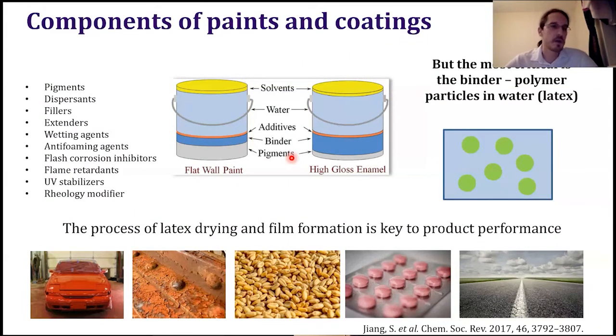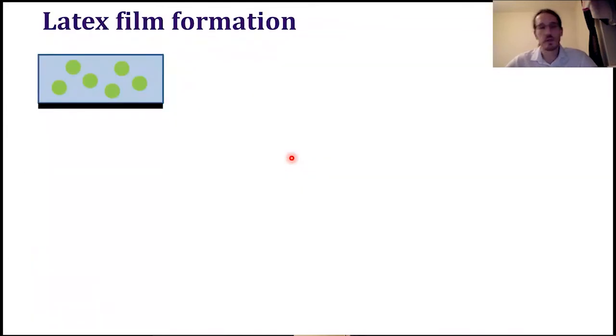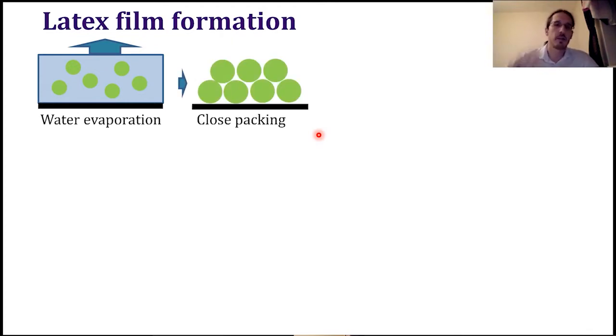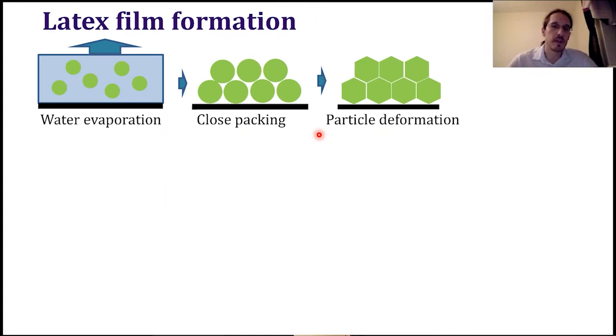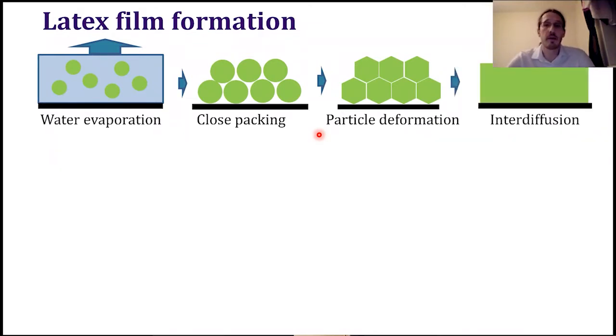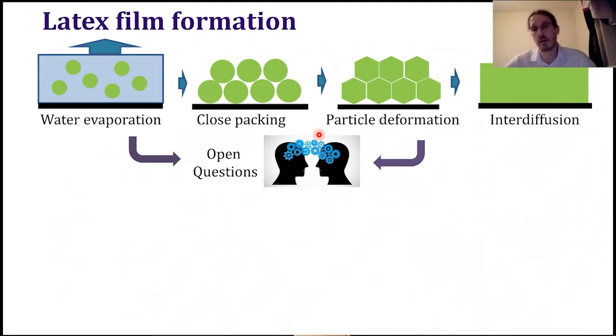So how does that process happen? Initially we have our polymer particles dispersed in water, and then the water starts to evaporate. As water evaporates, particles start to get close packed, hexagonally close packed, and the water completely evaporates. After the water is gone, due to surface tension, etc., we have particle deformation. The particles, because they are soft, tend to fill in the voids between them. And at some point, because they are polymer particles that can interdiffuse across those boundaries, they form a homogeneous coating all around. But despite seeming not to be an extremely complex process, there are still quite a lot of open questions in latex film formation.